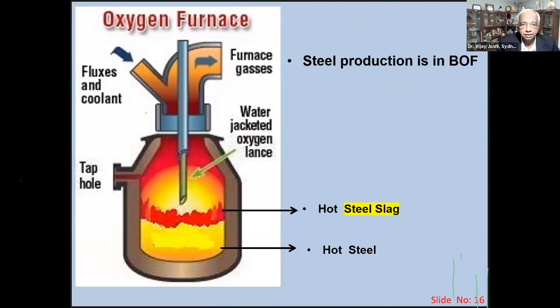Now that hot iron contains carbon, and we don't need carbon in the steel. So what they do is they get that hot iron, keep that in a big vessel, which is more than a 50 ton vessel, hot, covered, and then oxygen is forced in. You can see the oxygen lance is forced there. Once you have the hot iron with oxygen at 1500 degrees centigrade, a chemical reaction takes place, carbon is removed, and the steel is made.